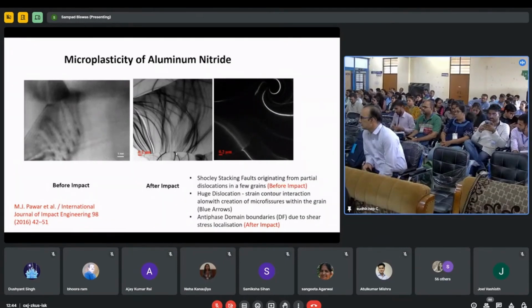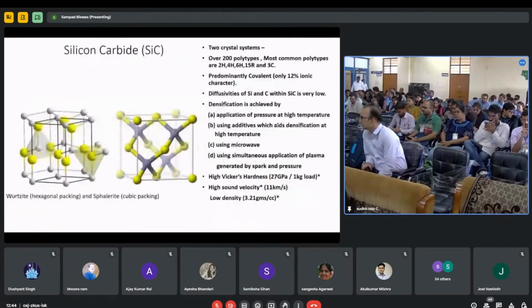So the original material is also very important. It is present, but in very minor quantities. But when it is shocked, you can see lots of domain boundaries are also there. These are the antiphase domain boundaries, and these are caused due to local shear stresses. So it absorbs a lot of energy, and this is a dark field image. You can see clearly the domain boundaries. So this absorbs a lot of energy of the impacted bullet. So this happens in the case of aluminum nitride, which is prone to ductility at a considerable confinement pressure.